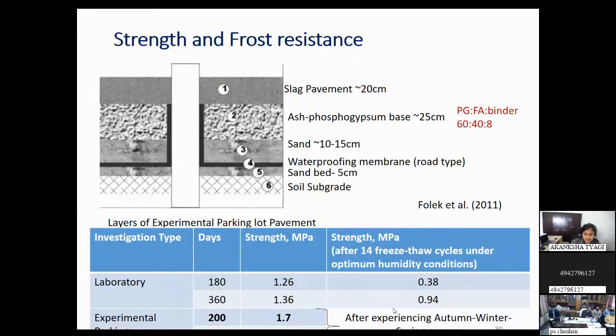And for that, they saw that the strength is lower. Quite low. But in the field, this kind of pavement system was experiencing autumn, winter, spring seasons. And in Poland, you can imagine the temperature fluctuations are quite high. So basically, in the field, this 1.7 MPa after 200 days and 5.1 MPa after 490 days, this strength is after experiencing that extreme climate.